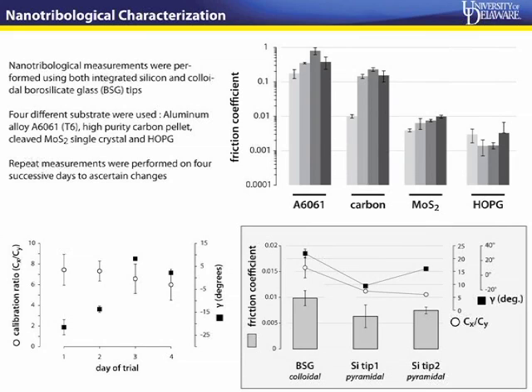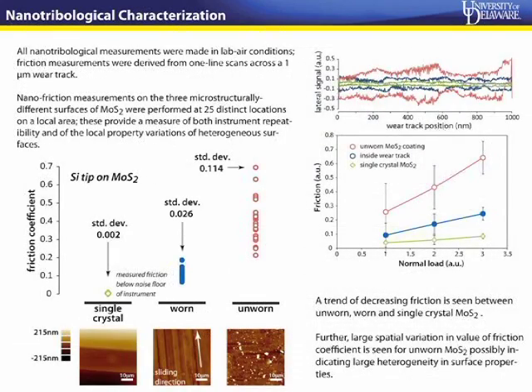Another series of tests was done on MoS2, to see what the effect of tribofilm formation was, because that's really what we're interested in with solid lubricants. This shows the test we did on a sputtered coating, the comparison between the unworn part of the coating and the worn part of the coating where you presumably have tribofilms, and as a control experiment we did single crystal measurements, which you saw earlier have a fairly low friction coefficient also.